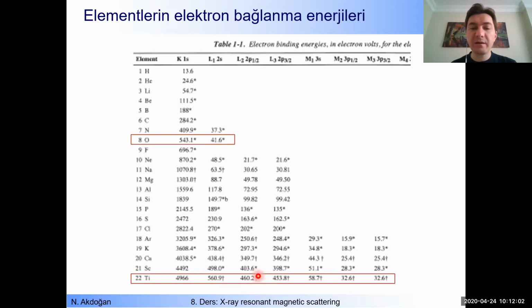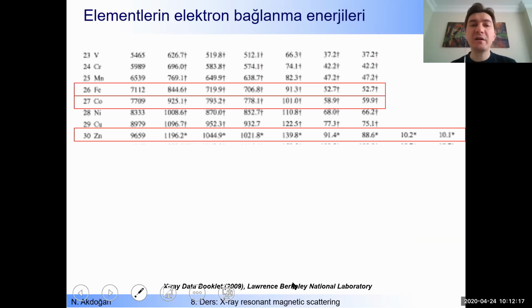So below 1 kilo electron volt, we have those energies for titanium, for example: 460 electron volts, 453 electron volts, something like this. If you are measuring iron, for example, these energies: 719, 706 electron volts. If you are dealing with cobalt, 793.2 and 778 electron volts. If you are dealing with nickel, these energies. If you are dealing with zinc, for example, these energies, above 1 kilo electron volt.